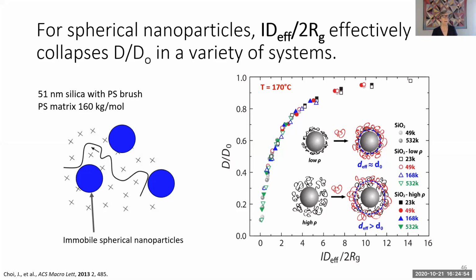So now let's just look at those results. So when the interparticle distance is very small relative to RG, the diffusion coefficient is going to drop by a lot, maybe even close to an order of magnitude when the particles are really tight, right? And that's going to impact how they respond in flow and how they respond to mechanical properties. But what's always interested me more, or maybe just as much, is that this is a very long range effect. So, we had to work really hard to make these very dilute nanocomposites systems, right? But now we're out at an ID over 2RG of more than 10, and we're still seeing a decrease in